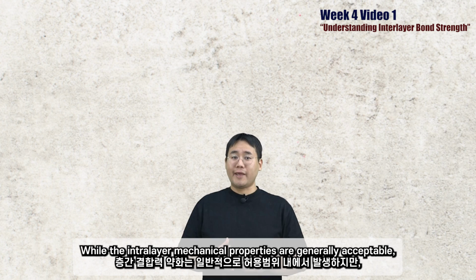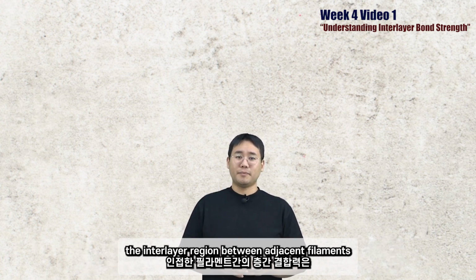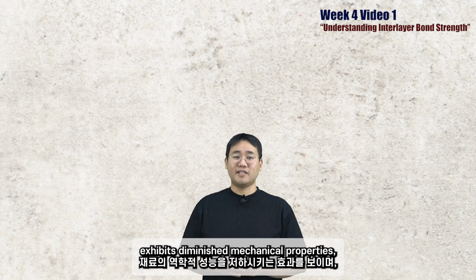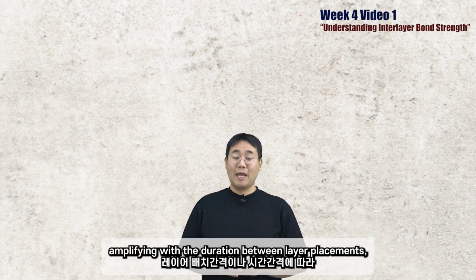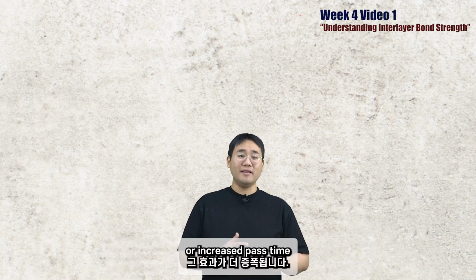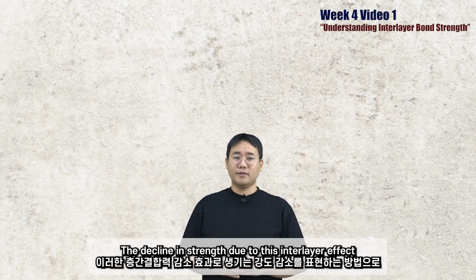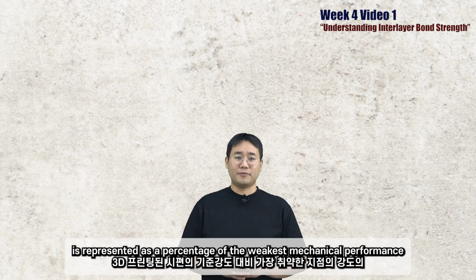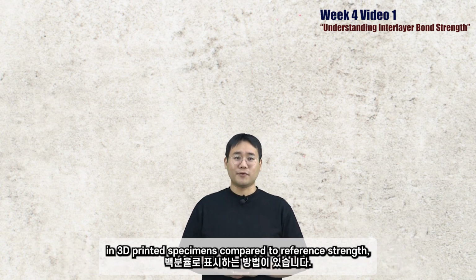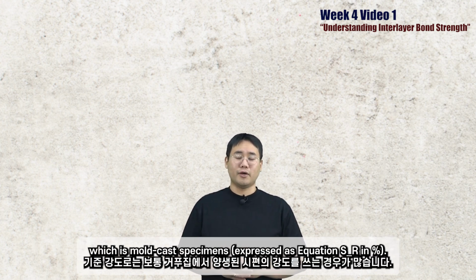While the intralayer mechanical properties are generally acceptable, the interlayer regions between adjacent filaments exhibit diminished mechanical properties, amplifying with the duration between layer deposition, or increased pause time. The decline in strength due to this interlayer effect is represented as a percentage of the weakest mechanical performance of the 3D printed specimen compared to reference strength, which is a mold cast specimen.